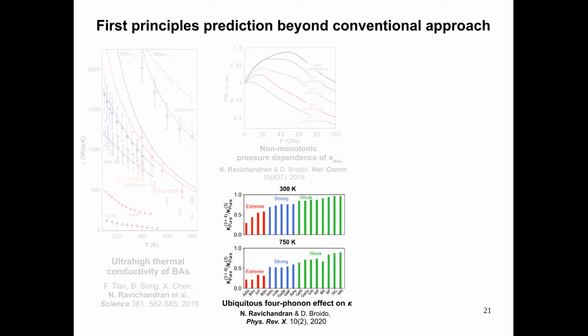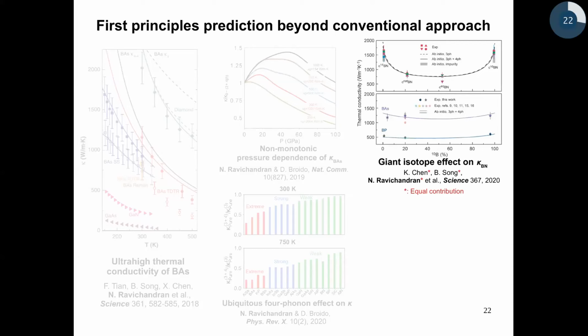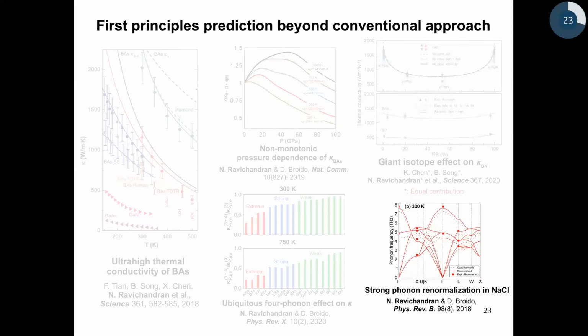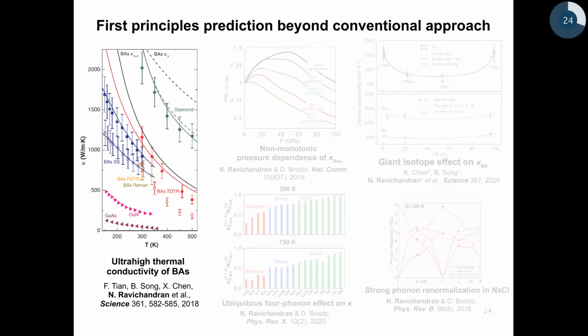example, here 4 phonon scattering, that is scattering among 4 phonons, is actually quite strong and ubiquitous among a broad range of even common 3-5 semiconductors. So my work has led to identification of the ultra-high thermal conductivity form of boron arsenide, that is cubic boron arsenide, through isotopic purification. And finally, also extending the conventional theory to include higher order effects in phonon thermodynamics. For example, the case of strong anharmonic phonon renormalization in ionic crystal sodium chloride. So this is a broad overview of the work that I have done using this approach, but I'll only focus on this first topic in this talk.